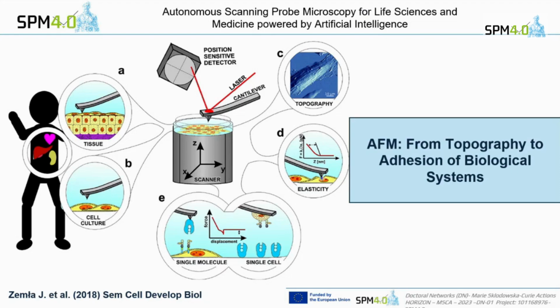Yeah, this is a very important factor because the best approach would be to measure the fresh sample, like directly from the biopsy. This is technically difficult because the equipment has to wait and then the data analysis. So we were evaluating that. We tested 3 different protocols. And from the tested protocols, deep freezing of the tissue is the best one because it helps to keep the properties of the tissue. And this is our paper from 2018.